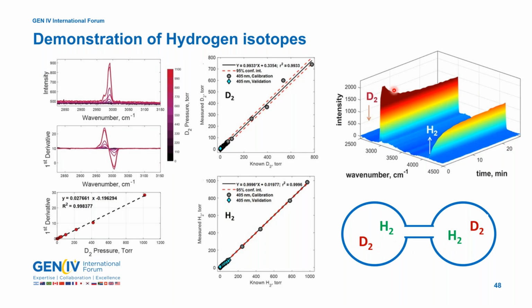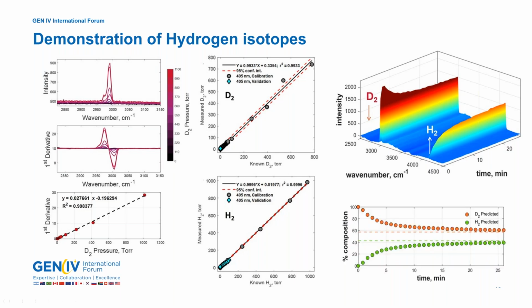So we see the deuterium over time, we see the hydrogen over time. These are the spectra as a function of time. We can then use our chemometric models to predict the concentration as a function of time. And so the composition is shown here. Deuterium decreases, the hydrogen increases over the 25-minute experiment time.